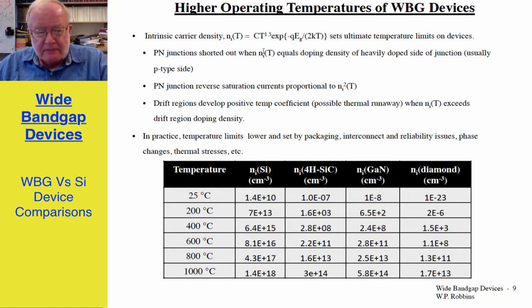The problem with this is, as the intrinsic carrier density gets larger than any of the doping levels, you're essentially shorting out the p-n junction. The p-n junction reverse saturation current is proportional to Ni squared, and so it's going to increase significantly as the junction temperature increases, even if you haven't reached the value of intrinsic carrier density that shorts out the p-n junction. In addition, the drift regions develop a positive temperature coefficient, leading to possible thermal runaway when Ni at the given temperature exceeds the drift region doping density.